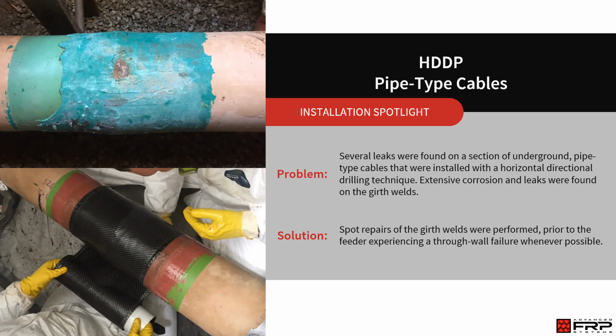Because we knew these were isolated leaks, we were able to do spot repairs. The key on this repair, doing spot repairs, these weren't particularly old feeder lines. We needed to tie back into the existing coating and not leave the opportunity for spot corrosion at the end of the repairs. So we were able to design a system that could be tied back into the existing coating. We were able to spark test it to verify that there were no gaps or voids in our coating system, despite the fact that we used a carbon fiber composite.